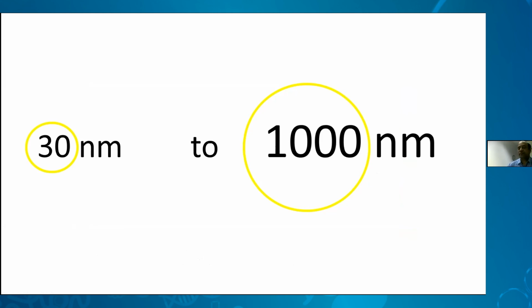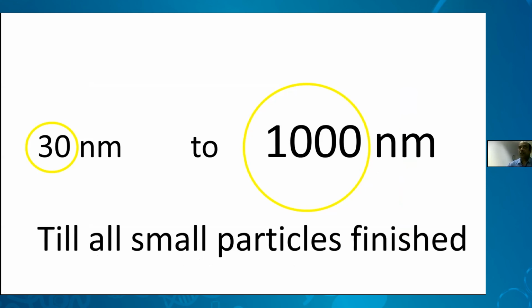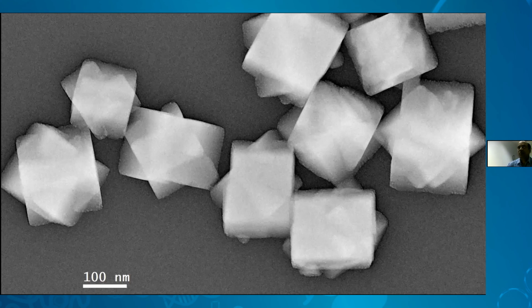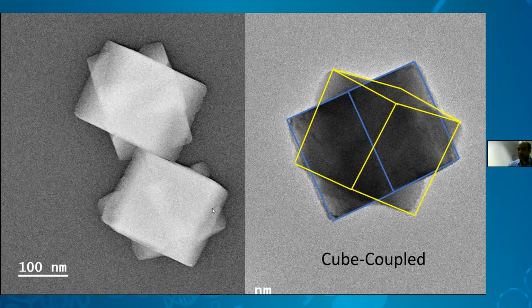These are truly flux chemistry magic in the flux chemistry. Here I would like to show that as I was talking, till all small particles are finished, the two cubes go on increasing. This is close to 200 nanometers, but it can also go further. And now the next structures, I'll show what these are exactly. You could see the TEM images. The left side images are the inverted TEM images, but these images you could see here are simply two cubes of the same materials. They are fused, and because of consuming all the smaller particles, these cube couples are formed. So with this, I would like to summarize the talk that crystal growth in the nano dimension can be